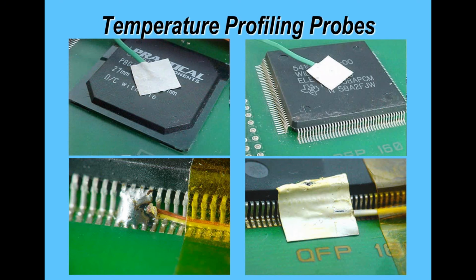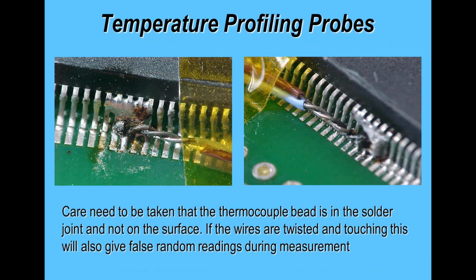This is normally done when you've got a very sensitive component that you want to monitor the top side temperature, but predominantly I use this when I'm profiling and setting up for rework of a package, because I want to know the surface temperature of the board, the solder joints, but I also want to know the surface temperature of the package during rework to make sure I'm not going to damage it in any way. And here's a couple of examples of how not to do profiling or mount thermocouples to a PCB. And just an example of something that I saw when I was working for a particular company, and of course highlighted the issues to the engineer concerned.